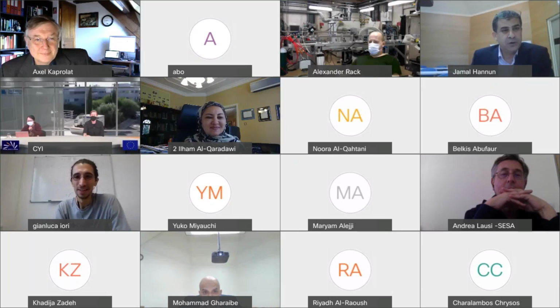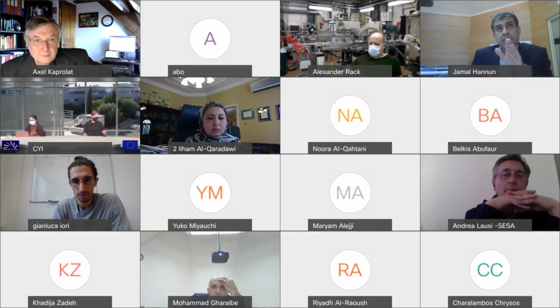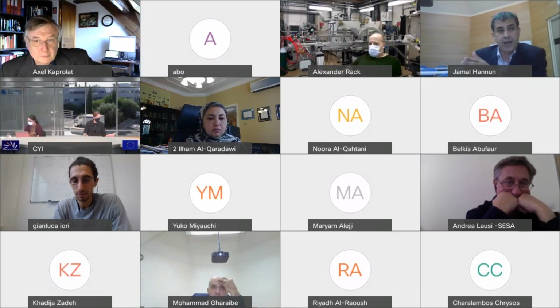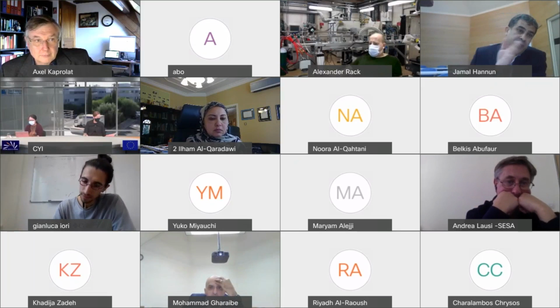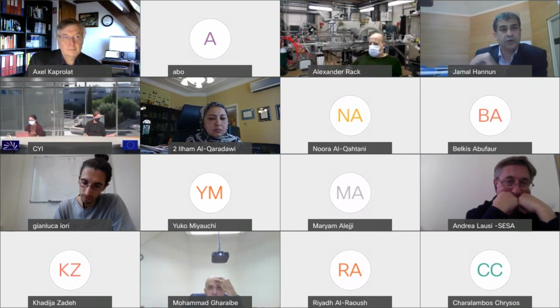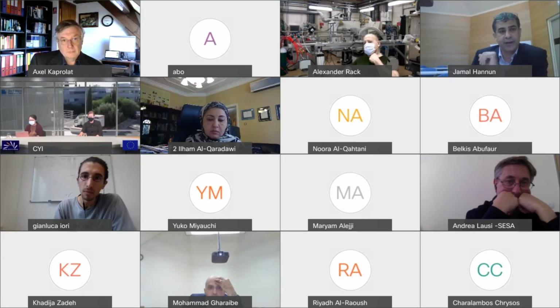Anyway, thank you. This is a very good question. So for the hydrate-bearing sediment, we are looking at the development of the hydrate, and the scanning time for the experiment was 12 seconds, and the running time was 4 hours for development of the gas and 4 hours for the dissociation. So it's about 8 hours of experiment. But the time of the scan is about 12 seconds.